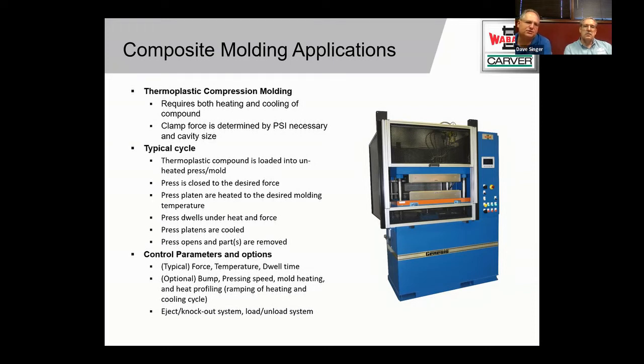But typically the cycle for the thermoplastic compound is that it's loaded into an unheated press or unheated mold, as opposed to a heated mold. The press is closed for a desired force, and then the platens are heated up, and usually it's a ramped heating rate. The press dwells under that heat rate, and maybe it's several ramps of the heat during that recipe. Then the presses are cooled, and those can be crash cooled, or they can be cooled at a controlled rate. After that, the press opens and the parts are removed again by hand or in an automated fashion. A lot of times on these, we're seeing all kinds of different shuttle systems, things like that, to get the material in and get the material out of the mold cavity itself.